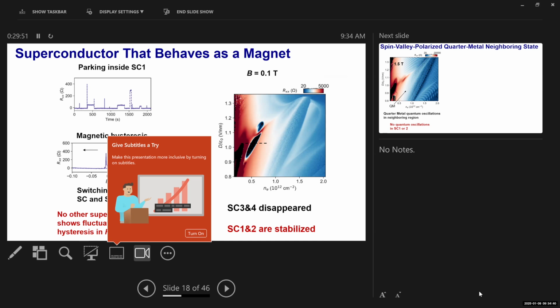To show you another map, this is taken at 0.1 Tesla magnetic field, which is beyond the coercive magnetic field of the hysteresis. So what happens in this case is you measure resistance again as a function of n and D. Suddenly, all those fluctuations are gone, because you are beyond the coercive field. 0.1 Tesla is able to completely stabilize one of the superconducting states, so that's why it's not fluctuating.